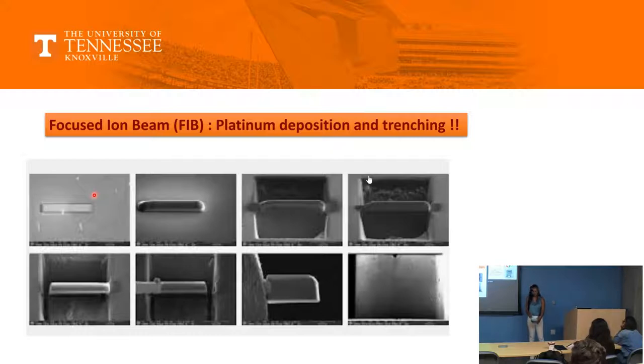Now what you do here is this: you know the zone that you want to analyze. You start depositing platinum like this. And once you have deposited the platinum, the idea is to take a very thin plate, exactly like a piece of paper, like a transverse plate. This is the same thing that you will do from here. And to do that, you have to create holes and try to make this region free from connections to either of the sides.